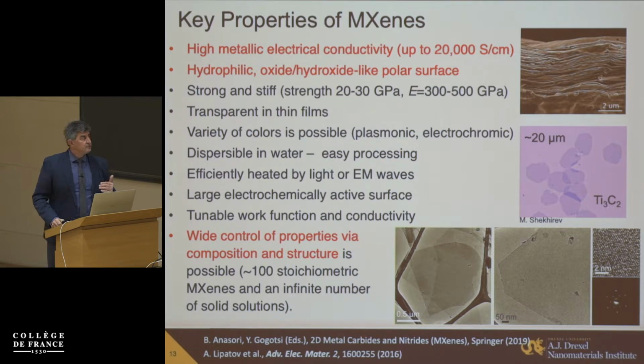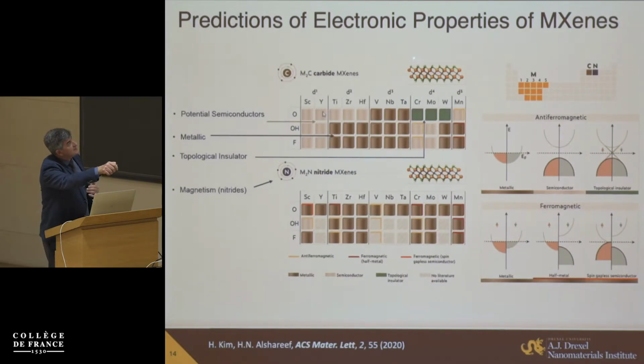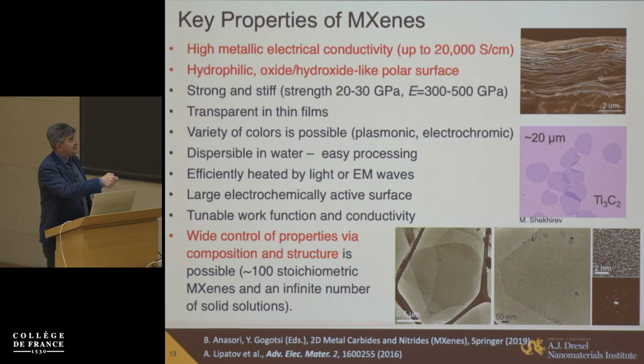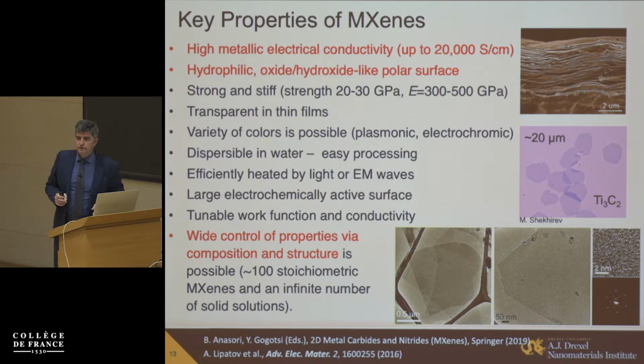Niobium carbide will be much less conducting because in such a thin structure, if you put oxygen on the surface, you pull electron density away, and you can open the band gap, at least as DFT says to us here. But they're also strong and stiff. Those are flakes produced from solutions, about 20 microns in size. I've never seen titanium or molybdenum disulfide flakes larger than a micron. That flake will simply break from vibration in solution. MXene, we can make it here.